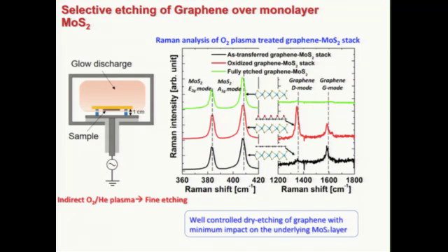We monitor it with Raman spectroscopy. This is the Raman spectra of the transferred stack of graphene on MoS2. So you see we have a G peak, and a very small D peak here. This is a CVD graphene, so it has some small defects. And these peaks are from MoS2. After a couple of pulses, we have a large D peak here. So graphene is fully oxidized. It's still there, but it's oxidized. And then finally, after a couple more pulses, graphene is completely etched away, but the MoS2 peaks are intact. So we can very selectively etch graphene over MoS2.